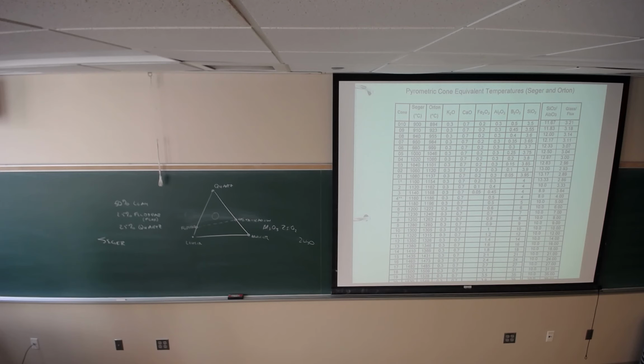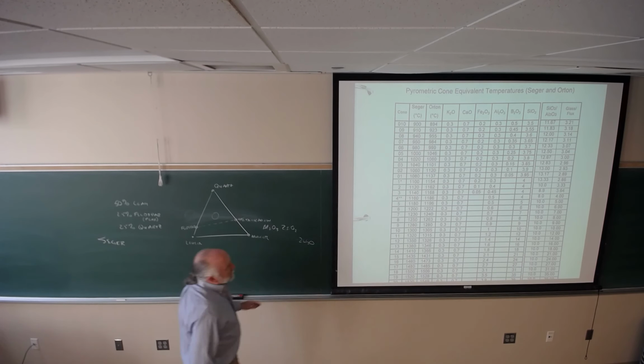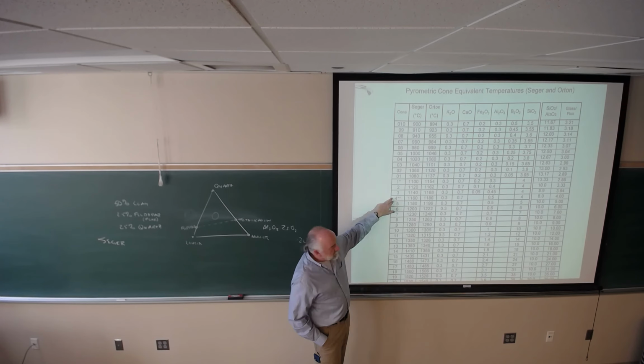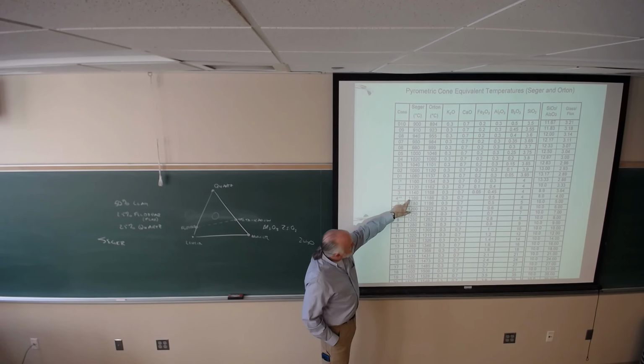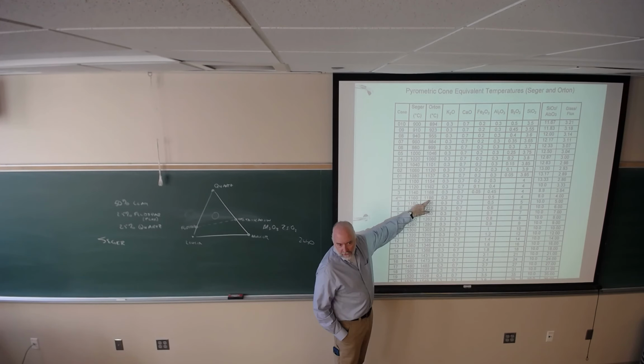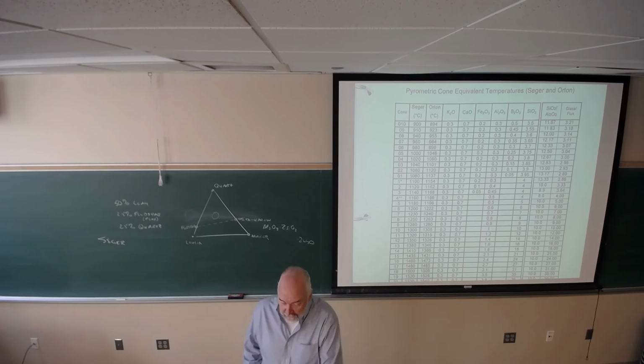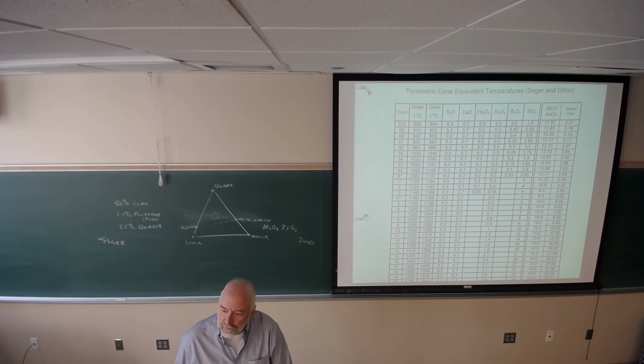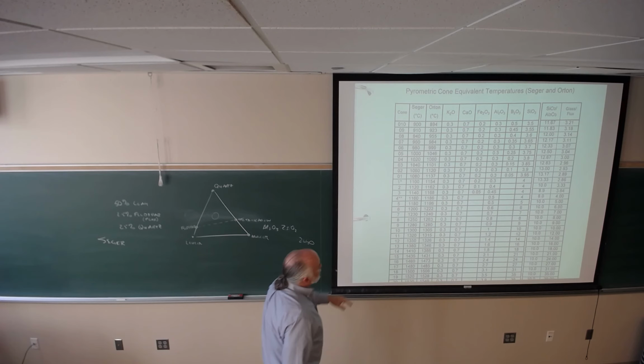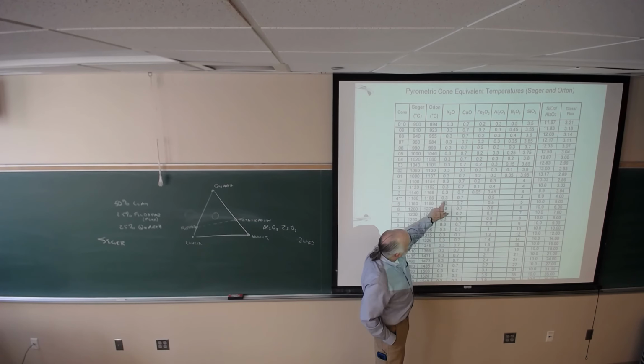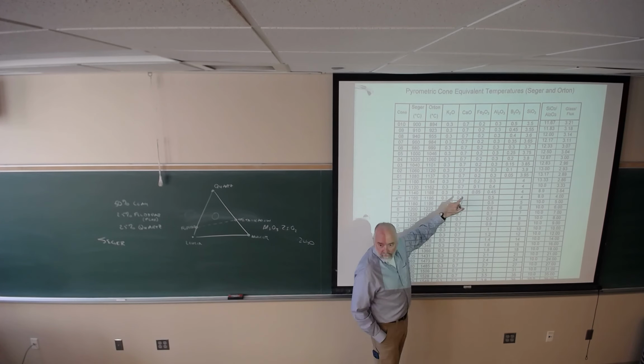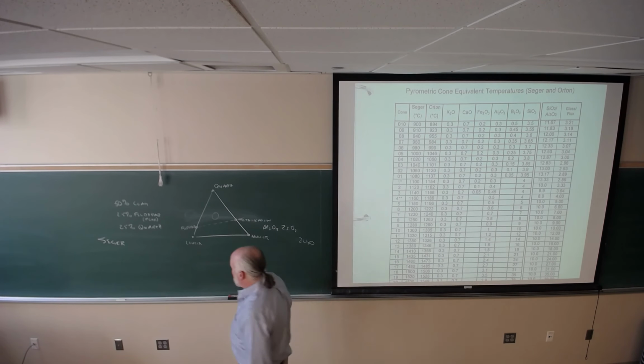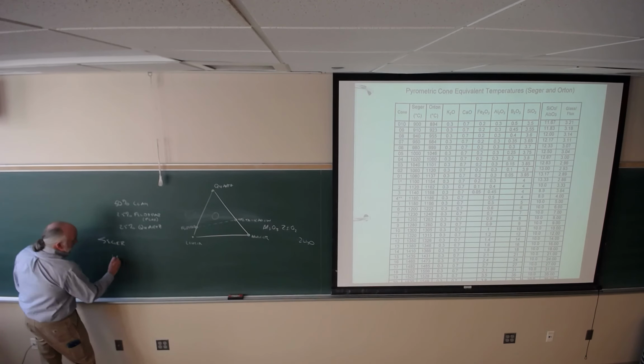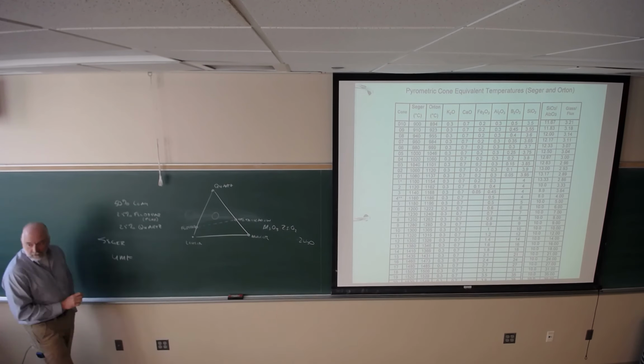And the first cone that he invented was, of course, cone 4. Why? Because he did the cones from a standpoint of chemistry, which is a really interesting idea at the time. Okay, and if you look across here at cone 4, it's got 2 stars by it because that's the first cone that was made. All right, and then his temperature, and then the temperature that we now know is correct. So based on 1895, I mean, you can give him some slack if he's off by 20 degrees, right? But the issue was that he made this cone up, and what you look at is the fluxes here, 0.3 to 0.7, so potassium and calcium, right? It equals 1. So what we have is called a Seger formula, or what we now call a UMF, a unity molecular formula, okay?